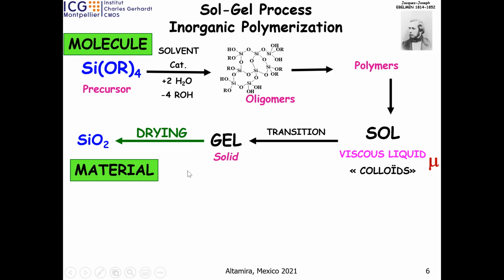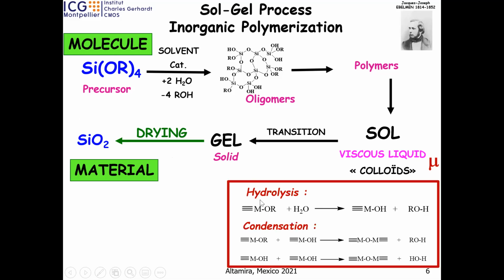After drying, you can remove the solvent by several types of drying. I don't talk about this. You obtain your oxide. Briefly, the main reactions are hydrolysis, a reaction between water and alkoxide to give metal hydroxide, and cross-linking, the connection between two silicon centers, which can be between two hydroxides or between hydroxide and alkoxide. So we obtain the same result at the end: silicon, oxygen, silicon, or metal, oxygen, metal bonds, and you release alcohol and water and so on.